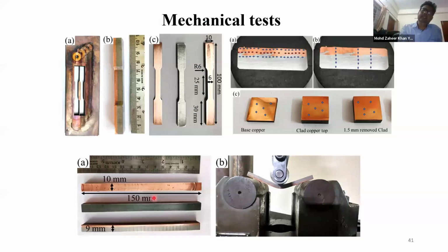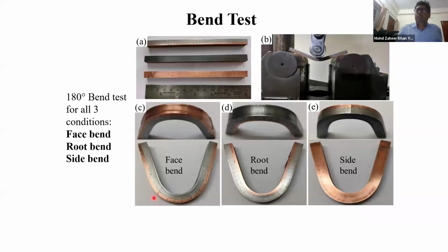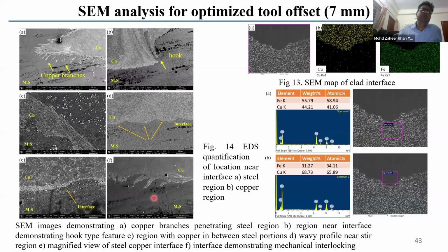This is the SEM analysis, and you can clearly see on the top portion, even in the mapped index, it is only mostly consisting of copper. In the bottom portion, it is mostly consisting of iron. So no mixing of the material has taken place, although there is firm anchoring of this that has taken place.